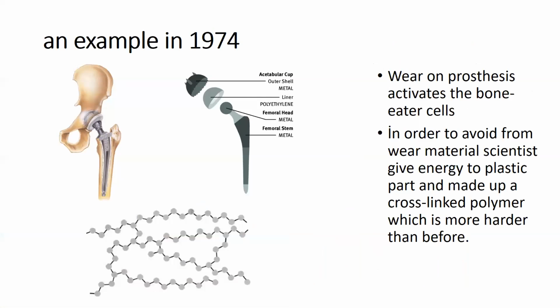One good example is, as we remember from our material science class, that after the first total hip replacement in 1974, doctors realized that bone tissue was diminished by the bone-eater cells. After cooperating with material scientists, they realized that bone-eater cells were induced by particles that ruptured from the plastic part because of the wear caused by walking. By giving energy, they made a cross-linked plastic which is relatively hard and resistant to wear, and they solved the problem.